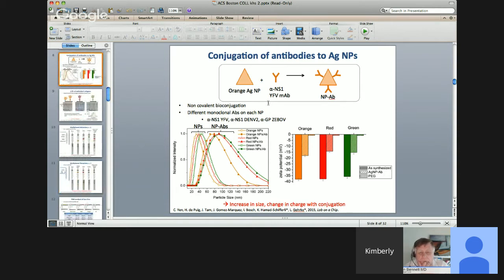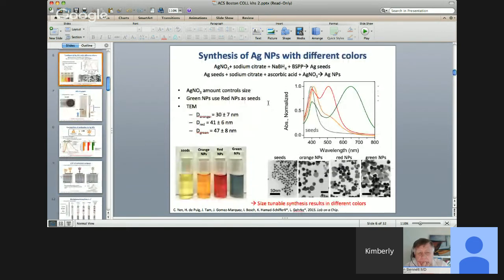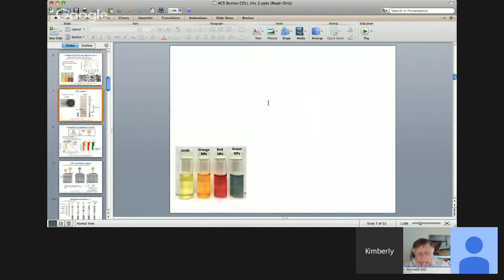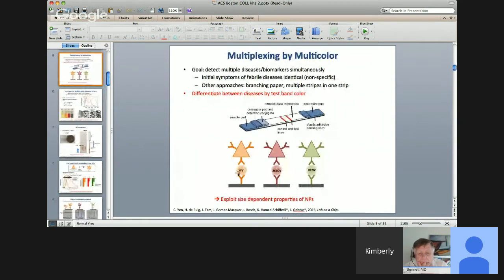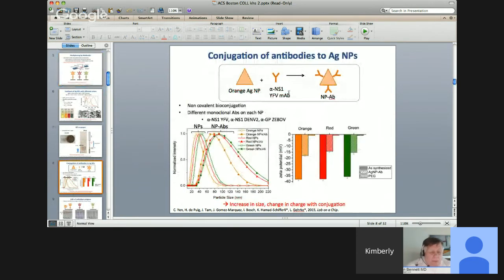We need, for this experiment, in order to get this sandwich assay where you can detect that biomarker of interest, you need to be able to put an antibody on the nanoparticle. And so what we did was we basically just let them stick to the surface of the nanoparticles, or you just incubate the two together, and they electrostatically adsorb on the surface of the particle, and this results in a nanoparticle antibody conjugate.